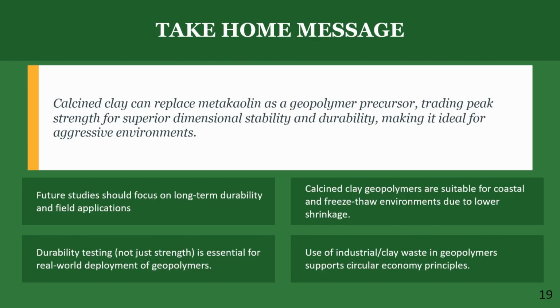Now, calcined clay can replace metakaolin as a geopolymer precursor, but the disadvantage is that it has lower strength compared to that of the metakaolin, which has superior strength, but it also has better dimensional stability and durability, making it ideal for aggressive environments. So the future studies, I believe, should focus on long-term durability. It's just a period of 90 days, and so future studies should look at maybe a period of 1 year and beyond to see how it fares.